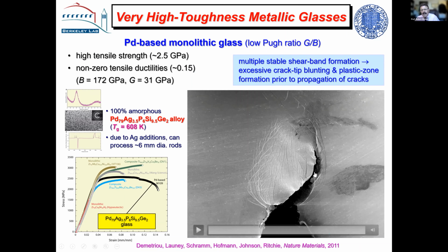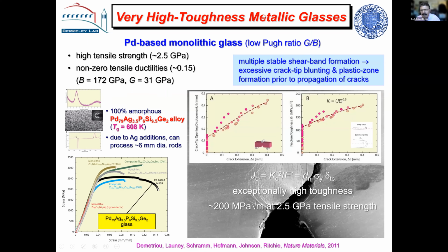And our philosophy of doing this was very simple. We said, well, if we have a low, I think this is called a Pugh ratio, a low shear to bulk modulus, the low shear modulus would promote multiple shear bands, but the high bulk modulus would prevent them opening to form cracks. And this worked. We got extremely high toughnesses. This is a fracture toughness R curve here. We're now close to 200 at the crack growth toughness with a 2.5 gigapascal strength material.